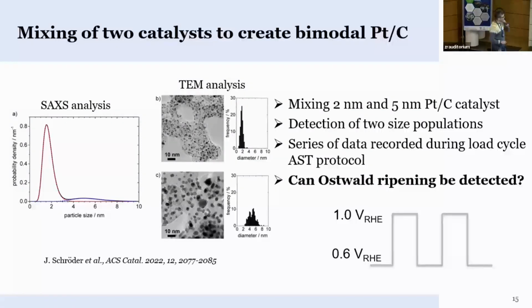So you can analyze the signal and you clearly see two contributions, one of the smaller particles and one of the larger particles. Whereas if you try to do that in TEM, it's very difficult to image this if you mix the powders. But in the individual TEM images, of course, you see the small population and the large population, and that's what you also get out in the analysis of the small angle X-ray scattering.